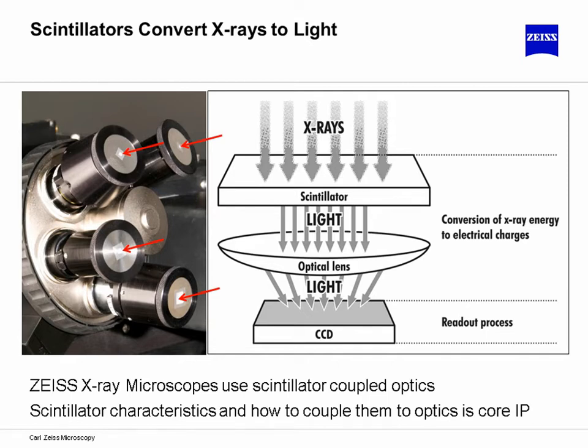And the trick to doing so is effectively this coupling of detailed scintillation and highly pure and well-controlled scintillation materials with an optical objective and a CCD detector that's sitting behind here. So the X-rays are converted to optical light. They're magnified primarily by this optical mechanism, which occurs after the sample, and then onto a CCD detector.